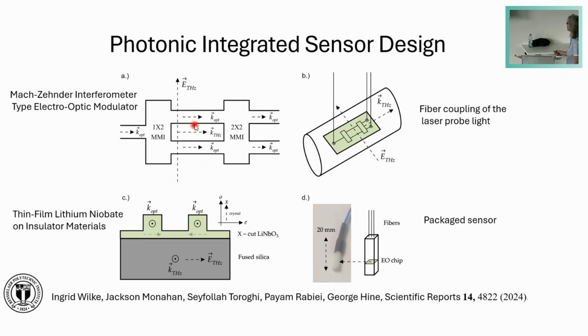Then the sensor operates in the following way. The optical laser light and the terahertz field have to travel in the same direction, and the electric field of the linearly polarized laser light has to be parallel to the two arms of the Mach-Zehnder interferometer. So this is the top view, and this is now the cross-sectional view. We have approximately 600 nanometer of thin film lithium niobate on an insulating substrate, fused silica, which is 500 micrometer thick.